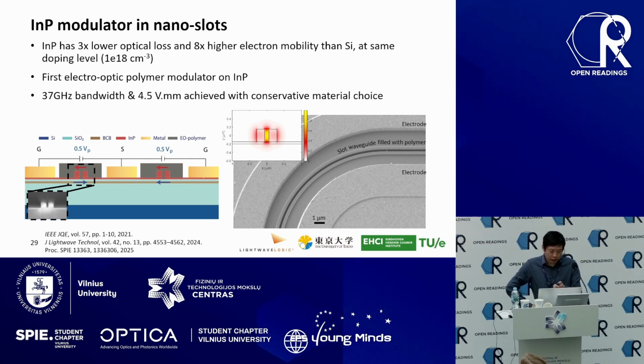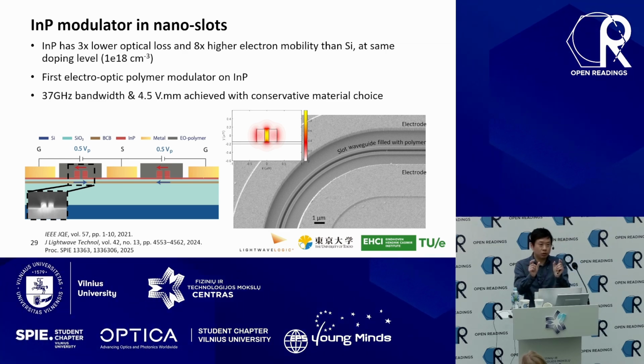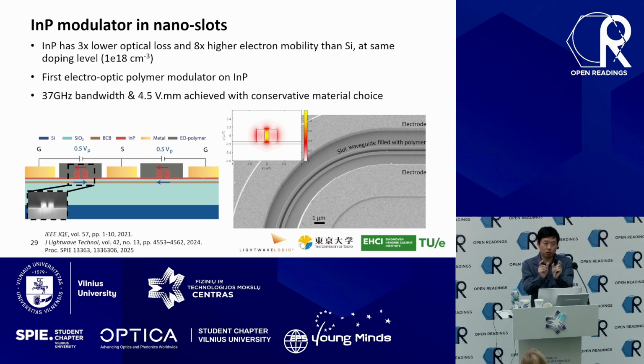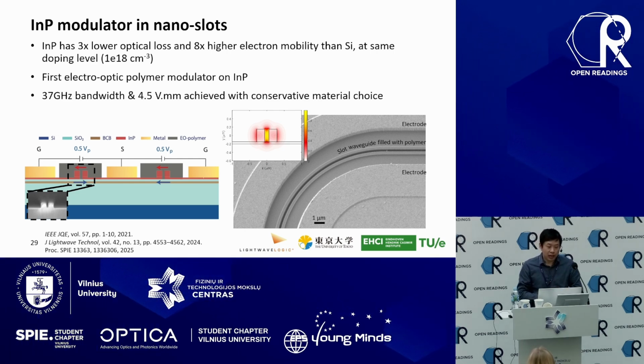Because we created such a slot waveguide, as you can see in the mode profile in the middle, by placing 2 waveguides extremely close to each other, leaving only a 100 nanometer gap. Actually, most of the light intensity is not in the waveguide, but in the slot in between. It's quite commonly known, right?